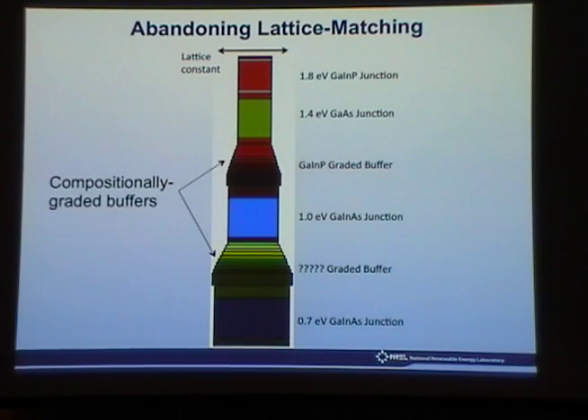I mean, there's going to be some recombination in each of the junctions, sure. So it doesn't matter whether this recombination is on a dislocation free or on a dislocation existing interface. There's going to be some recombination inevitably. What you would love to have in an ideal world is that be completely radiative. In other words, the result of that recombination is you emit a photon. Okay? If you don't get radiative recombination, you get non-radiative recombination. You totally lose the electron from the system. And you're going to have some of that regardless.